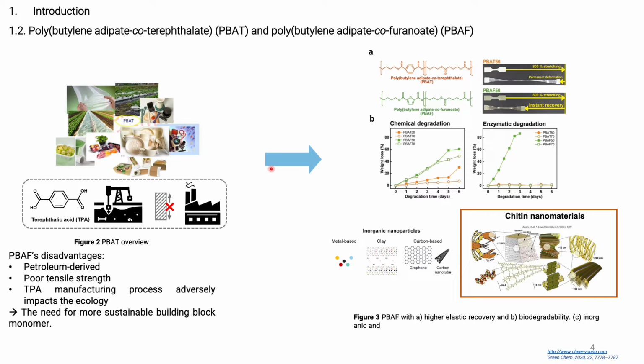In our previous study, we have synthesized polybutylene adipate-co-furanoate, which is PBAF. The polymer exhibits a higher biodegradation in chemical and enzymatic conditions, as you can see here. And also it has a superior elastic performance and competitive mechanical properties compared with those of PBAT. However, the tensile strength and toughness of PBAF still need to be further improved in order to compete with commercial bio-based and biodegradable plastic film.